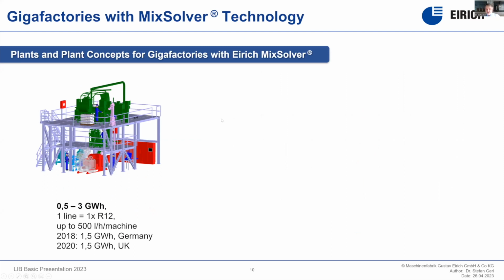Now, how different gigafactories could look like. We have different concepts. One is for low capacity applications, typically in the range of 0.5 to 3 gigawatt hours, which means at the end we have one mixer located on the ground floor. As Michael has shown before, we have a 2- or 3-story system. On the top level, we have the bag and big bag handling station. We have a second floor with the automatic dosing system to achieve the necessary accuracy, and powder dosing. And we have all the liquid dosing and liquid transfer systems on the ground floor together with the mixer.